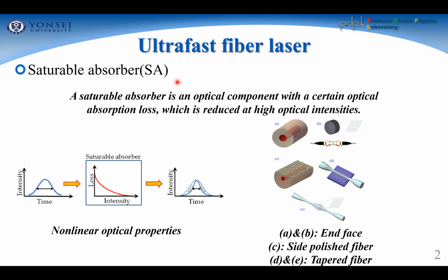My research focuses on saturable absorbers, which are optical components that make very short wavelength pulse generation components. The principle of the saturable absorber is that low intensities have high losses and high intensities have low loss. It can make a very short pulse like this. So we use the nonlinear optical properties of the materials. We can make very short pulse lasers by using a saturable absorber.